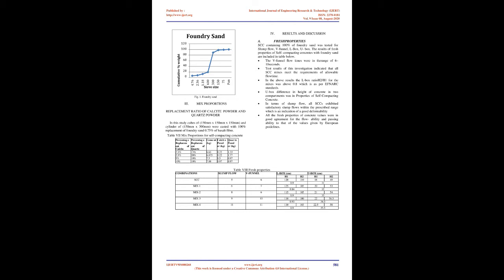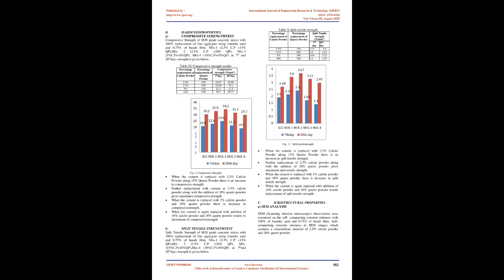In order to overcome the disposal problem of industrial waste and to reduce the construction cost, waste foundry sand has been used. This paper gives remarkable results which indicate that foundry sand is economical, and found that 30% replacement of waste foundry sand gives maximum compressive strength and flexural strength at 28 days. It was concluded that waste foundry sand is a good replacement of fine aggregate and helps in preparing green concrete.